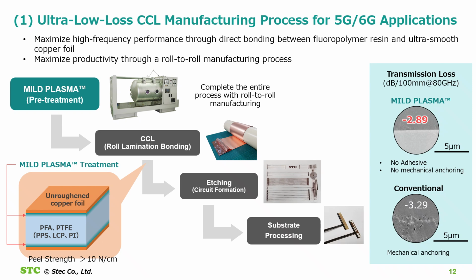Our record shows the peel strength of the bonded fluoropolymer to copper structure was over 10 newtons per centimeter, and transmission loss was minus 2.89 decibels per 100 millimeters at 80 gigahertz, compared with minus 3.29 for the conventional approach.